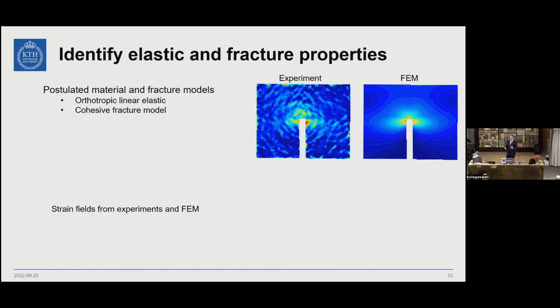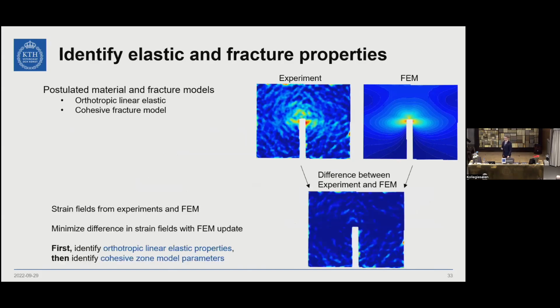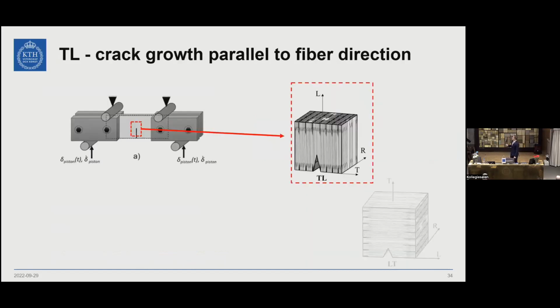Like I said, we can use the strain field measurements. We can compare them from experiment with the finite element model, and we minimize the difference between those two to identify the properties. So first the elastic and then the fracture properties. Looking at the weakest direction.